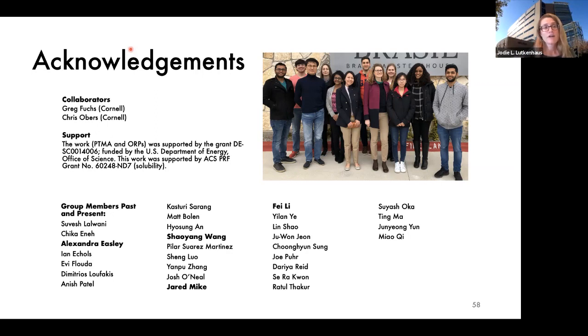In a battery environment, as the polymer goes through its states of charge, its solubility will most certainly change. And for PTMA, my opinion is that it is most soluble in its nitroxide radical form based on what we're seeing. So if you want to think about solubility, worst case scenario, you could go to a nitroxide radical polymer that has a lower content of the oxoammonium cation, because it seems like the oxoammonium cation form is not soluble in anything, not even water, which I thought was kind of interesting.